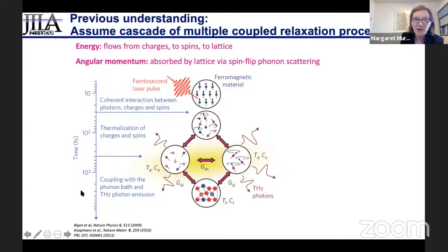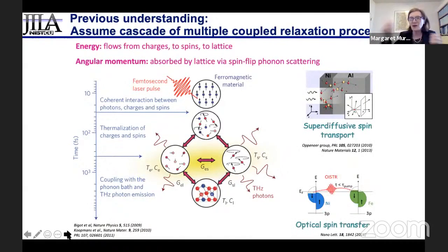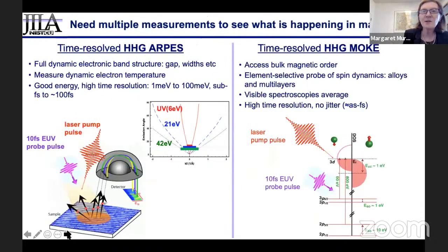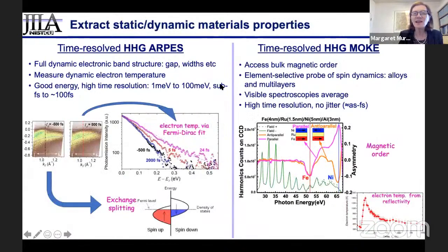Now, what was strange about this is that all materials had roughly the same demagnetization curve. And there were theories that seemed reasonable that predicted a very fast spin transport or direct excitations, but nobody ever saw any evidence of this in the material responses. But by using a bunch of different spectroscopies, and those in chemistry know this very well, every probe measures something different about the materials. And the one very powerful probe is photoemission spectroscopy. So let me just talk about that. Why is that so powerful?